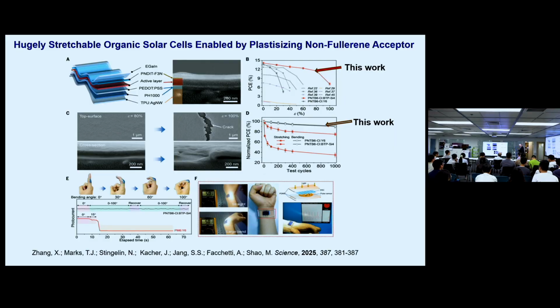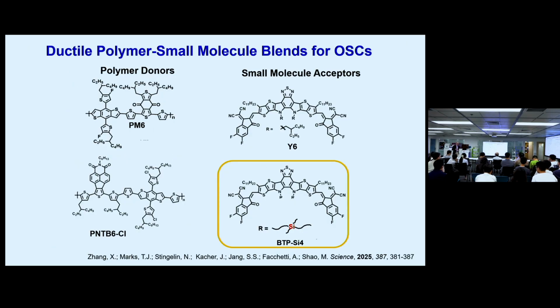So there's one component that no one ever thought of before, which really is the key thing here. And the acceptors, these are the crescent-shaped acceptors, but what we did, so on the left are the two donor polymers, and on the right, we've taken the Y6, the classic one, but for these R groups here, we replaced them rather than just a hydrocarbon chain with a silicon in the chain. And you might say silicon is just a big carbon. What's the big deal?